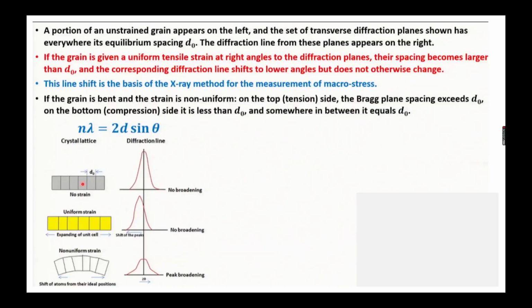Okay. So when you have an unstrained grain, it appears on the left, and the set of transverse diffraction planes shown is everywhere. Suppose there is no broadening and no strain, you have a center. Suppose we have applied a uniform strain, so your unit cell will also expand in this way, right? So firstly, your peak will shift to the left. Again, because this is a uniform strain. When you apply a non-uniform strain, the atoms will shift from their ideal position. In that case you will get a big broadening.